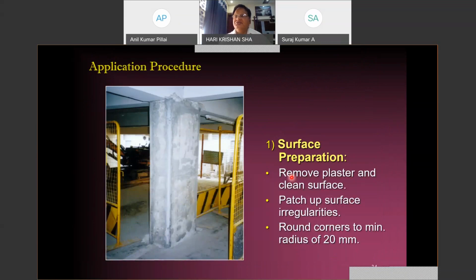As far as the application of this material is concerned, this is a very interesting phenomenon in the sense that the structure which you want to retrofit has, first of all, to be prepared. As far as the surface preparation is concerned, we remove the plaster and clean the surface, then patch up the surface irregularities, and all corners are rounded off to about 20 millimeters. So these corners are rounded so that when you apply the FRP sheet all over the column, there will not be ingress of atmospheric gases from the corners.